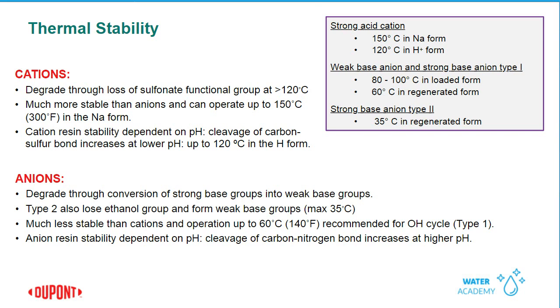Unlike the case of free chlorine where the cation resin takes the brunt of the attack and the downstream anion in a two-bed system remains somewhat protected, we do have evidence that with chloramines, this can cause damage in both the cation and the anion because it has a different mechanism for the reaction. So our recommendation is that if you have switched from chlorination to now using chloramines, then we would recommend a review of your upstream pretreatment to make sure that you're removing these oxidants because they can damage not only the cation resin but also the anion resin.